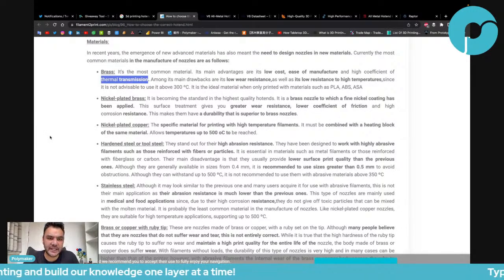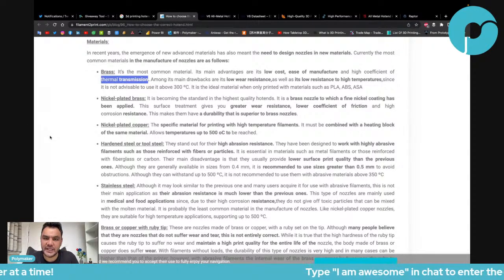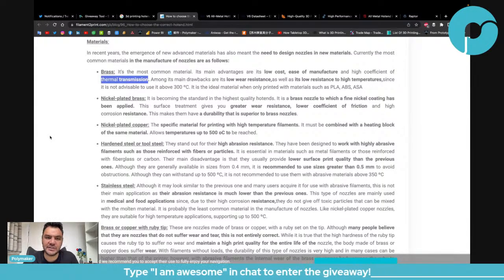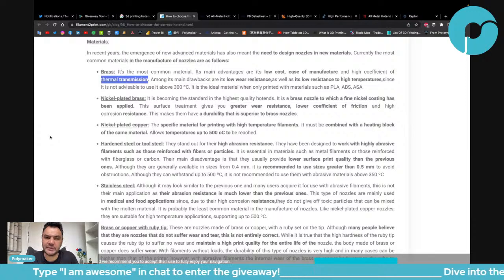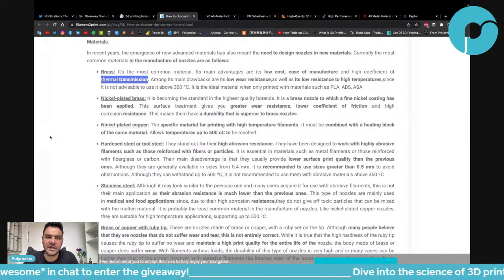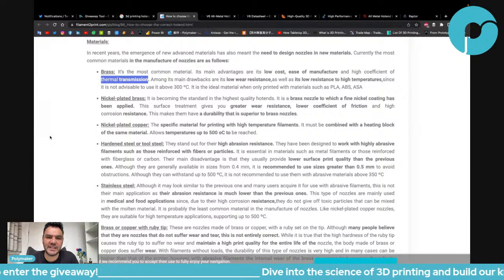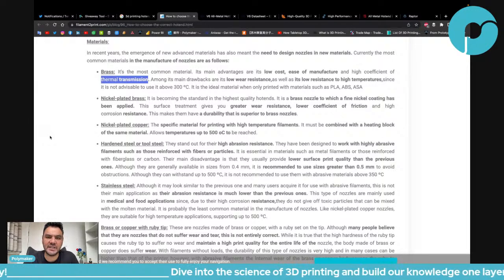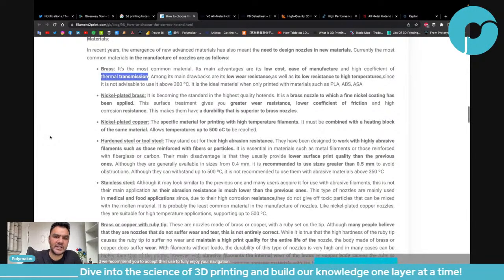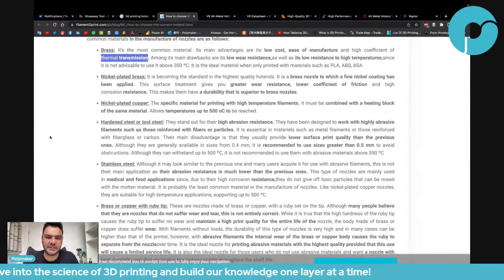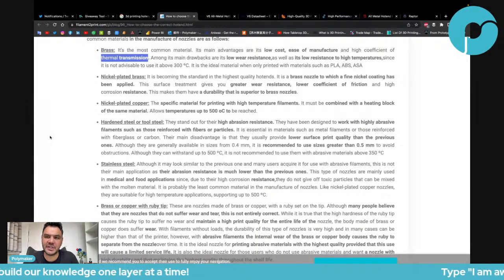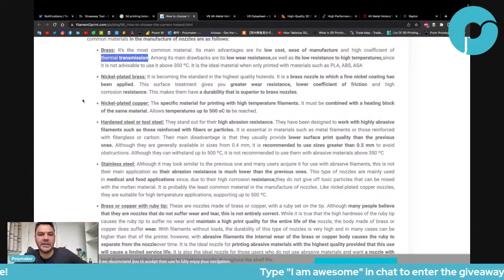Nickel-plated brass. It is becoming the standard in the highest quality nozzle. It is a brass nozzle to which a fine nickel coating has been applied. This surface treatment gives you greater wear resistance, lower coefficient of friction, and high corrosion resistance. This makes them have a durability that is superior to brass nozzle. Okay. Nickel-plated copper, the specific material for printing with high temperature filament. It must be combined with a heating block of the same material, allows temperature up to 500 degrees.